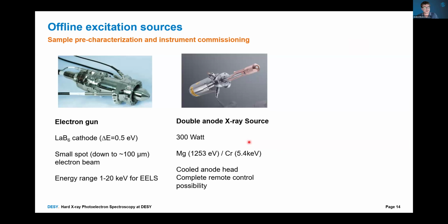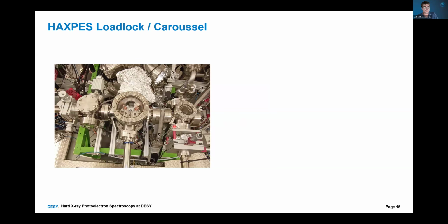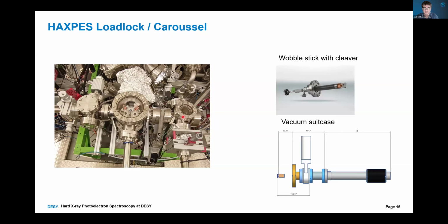Also, we offer offline excitation sources like an electron gun for EELS spectra to study plasmon losses of the sample, and a very standard double anode X-ray source for lab XPS if we are in shutdown or if the synchrotron is offline. Here is our load lock and distribution chamber. So we load the samples to the load lock, which is permanently vented, and the distribution chamber is always in UHV. It can carry up to 12 samples. And the load lock serves as a preparation chamber.